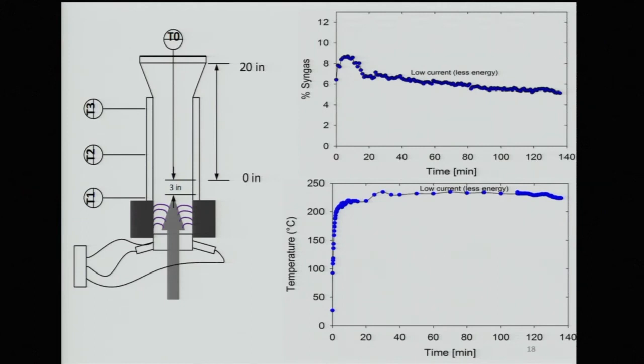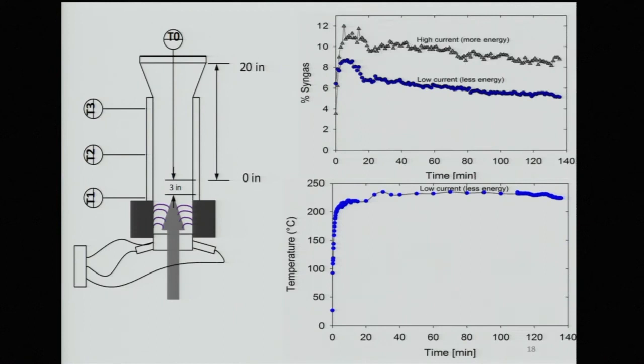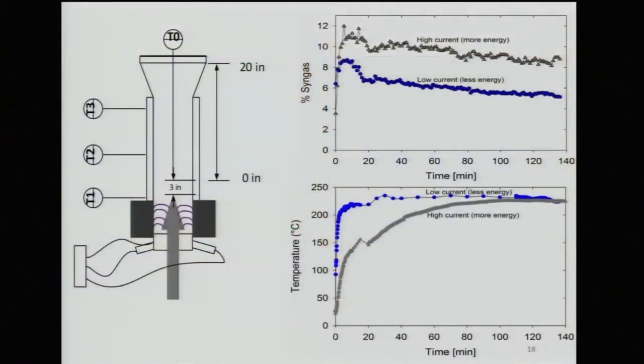We are giving more energy to our process. So we were expecting more conversion, and we get more conversion. We have more syngas. But giving more energy will also imply, logically, to have more temperature. But surprisingly, we didn't find it. We have a smoother slope, and it reaches a steady state around minute 100. So the increase of temperature is not as high as in the other curve.